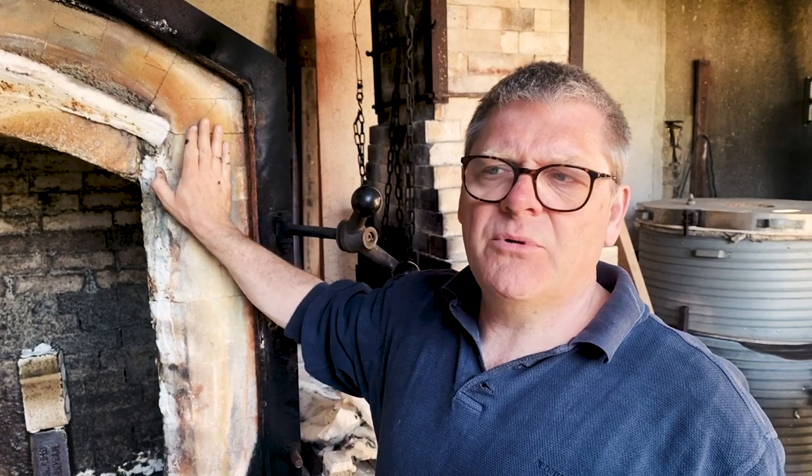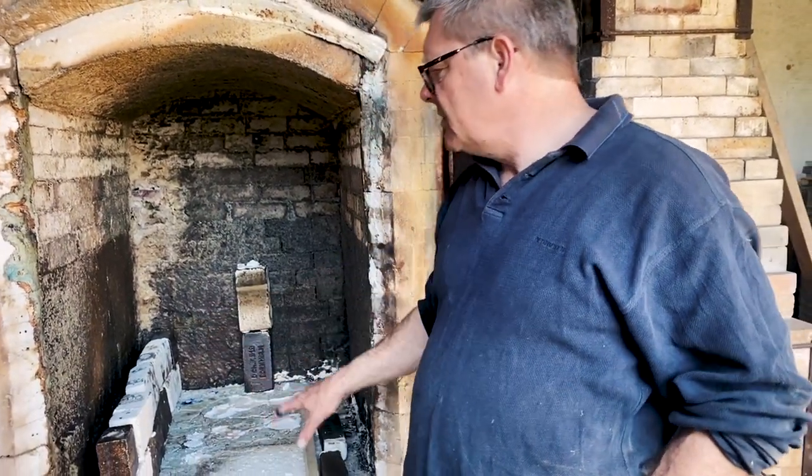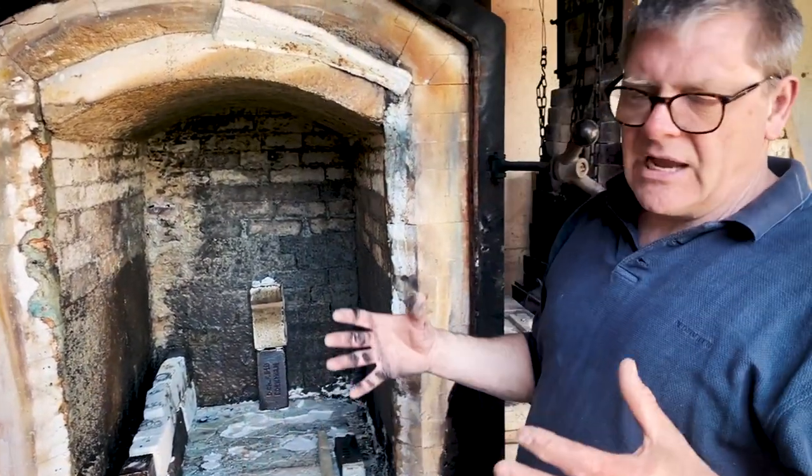Conclusion of the firing is that the firing was too pale, and we had problems with the temperature in the front, and especially in the lowest part of the front. So we will change the firewall so that it gives some more open space, and we will have a more open kiln packing for next firing, so that we more easily can get the temperature. When we do that, we can also get more reduction, because if you struggle really hard to get the temperature, you will hesitate to make too much reduction, because reduction reduces temperature,